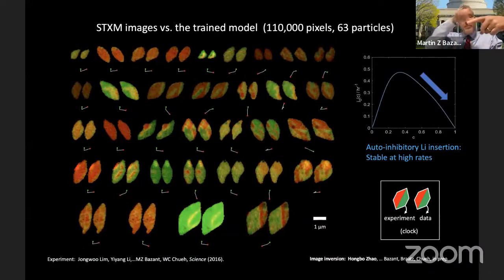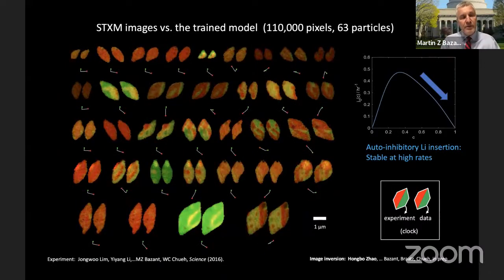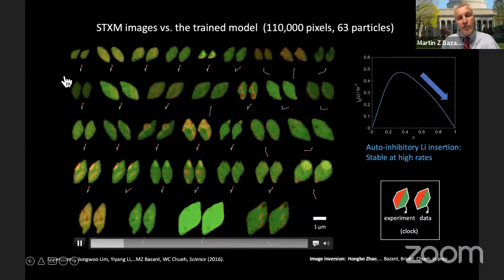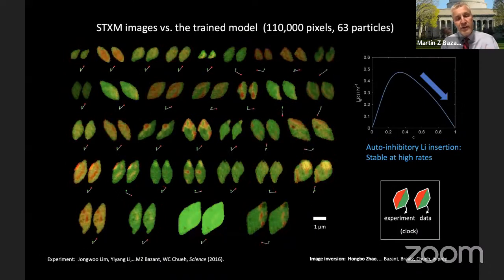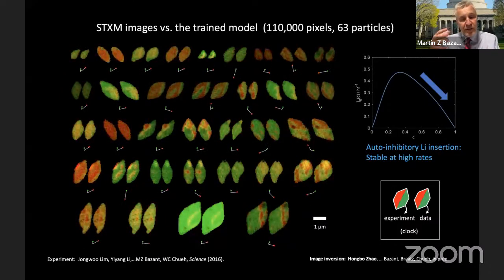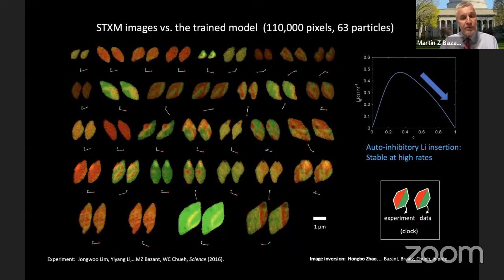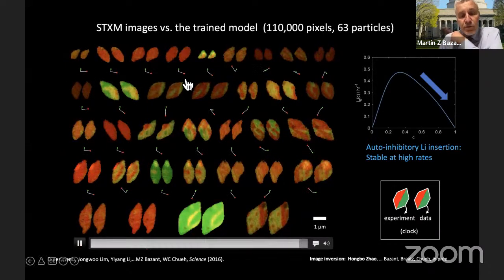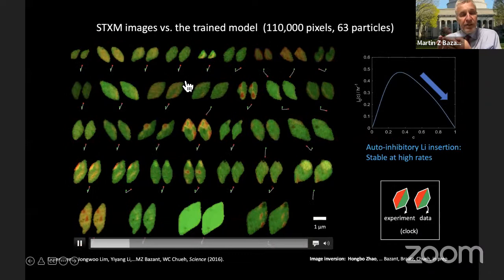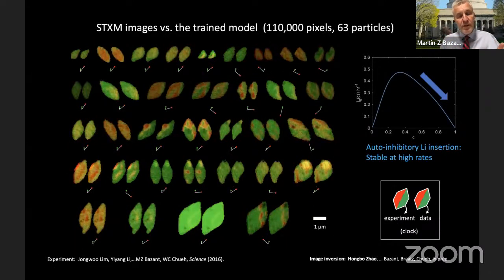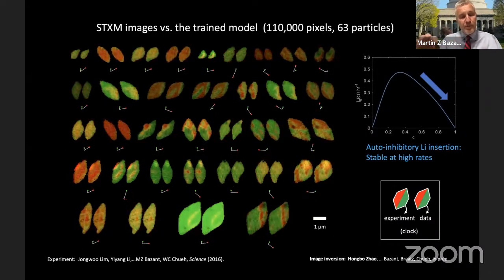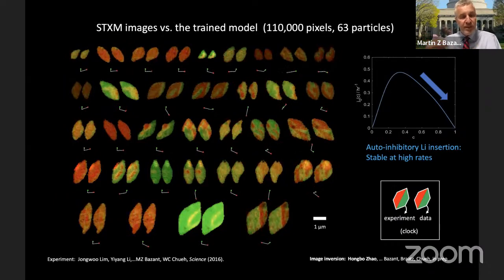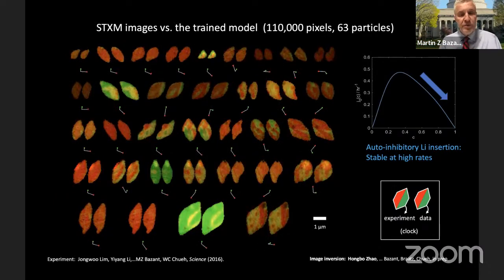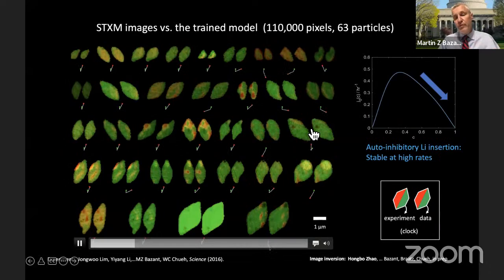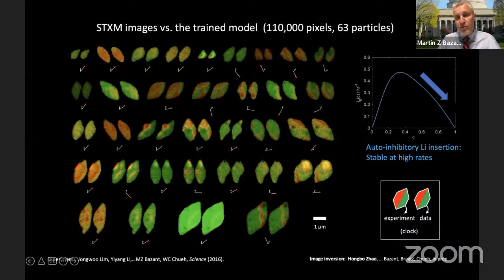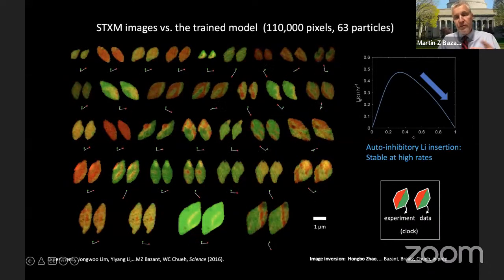And the little thing spinning around is the clock, because some of these particles are cycled at low rates and some of them are cycled at high rates. And in a number of cases, we have the same particles cycled at different rates. And we assume that the thermodynamics and reaction kinetics are the same for all particles, but each particle has a spatially dependent rate constant having to do with heterogeneity of the carbon coating on the surface. And what we do learn is that there's this autoinhibitory insertion rate.